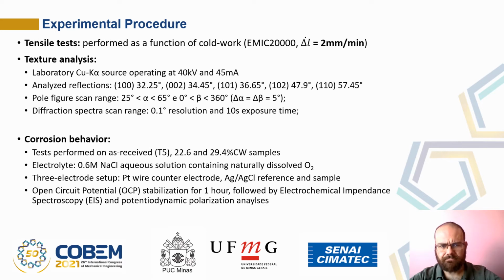After each drawing step, samples were evaluated concerning their mechanical strength by tensile testing, and crystallographic texture analysis by X-ray diffraction was also performed. These were carried out in a laboratory copper K-alpha radiation source. The reflections which were analyzed were the 100, 002, 101, 102, and 110 reflections. Pole figure data for analysis were obtained in the 25 to 65 degree range in the tilt direction, and from 0 to 360 degrees in the azimuthal direction. The individual diffraction spectra were acquired with a 0.1 resolution and 10 seconds exposure time.